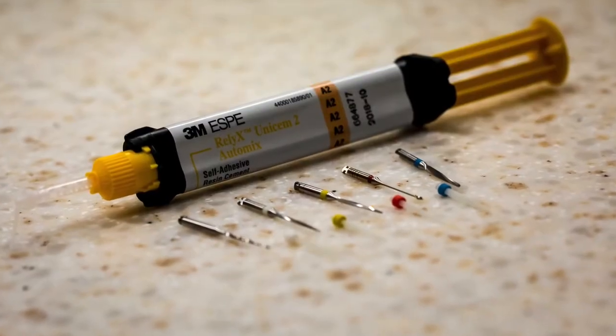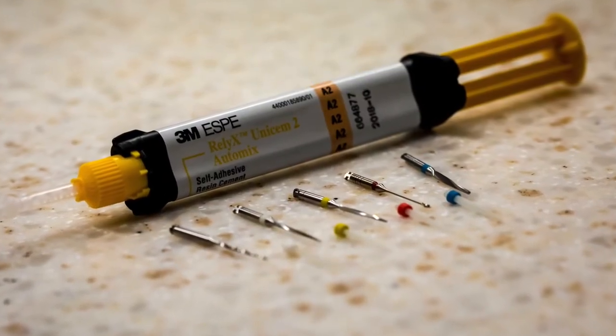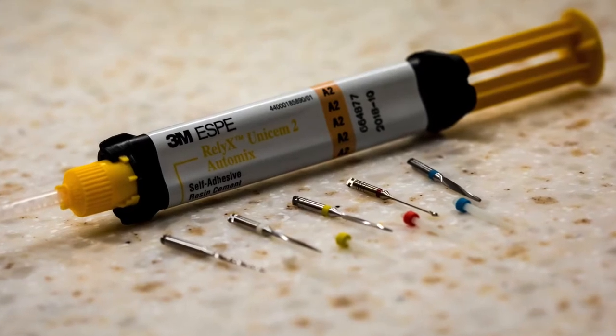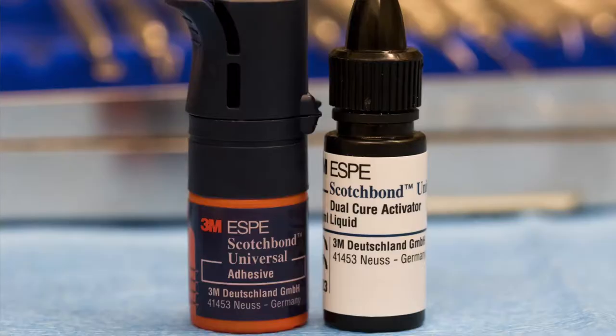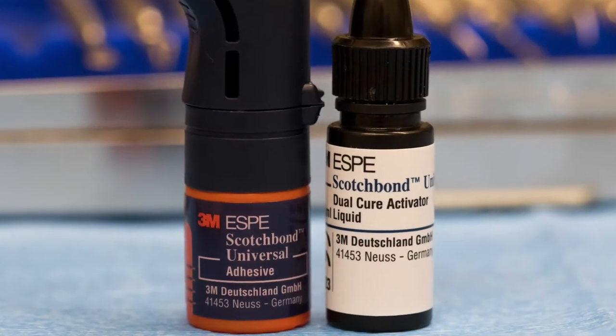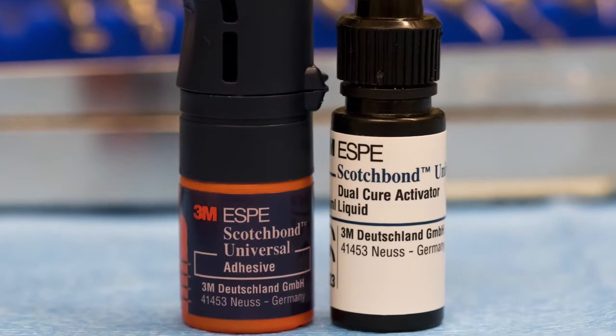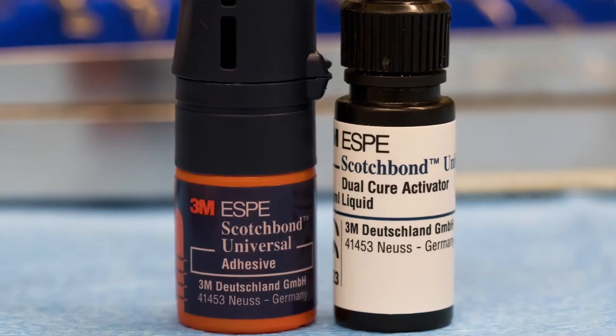However, let's say, for example, you wanted to use Relyx Unicem, another product by 3M. That specific product does not actually contain a dual cure activator. So if you're going to use a universal adhesive like Scotchbond Universal with that specific cement, you have to add a dual cure activator to the Scotchbond before you actually cement with Relyx Unicem.